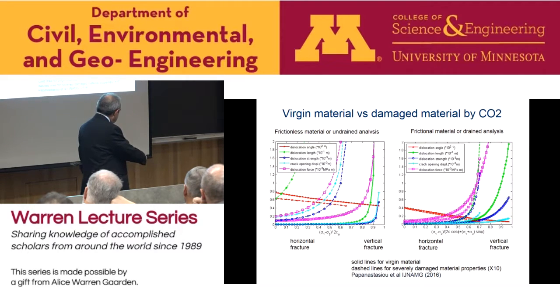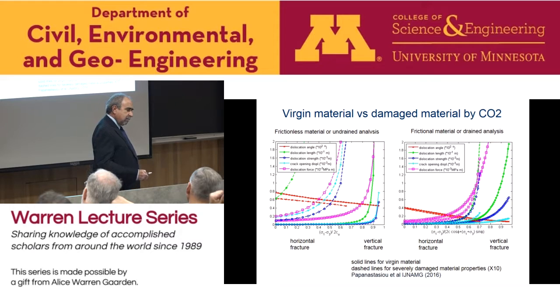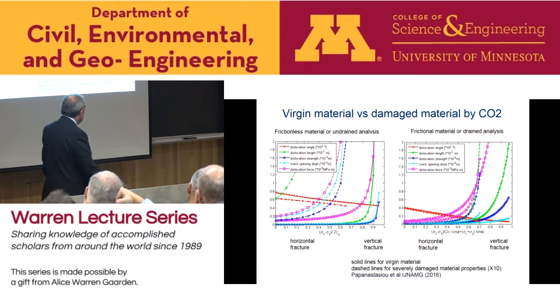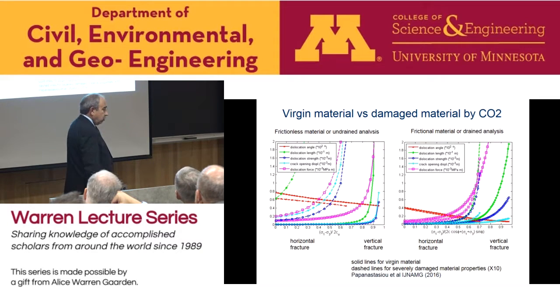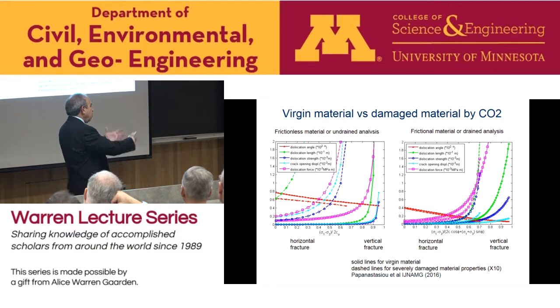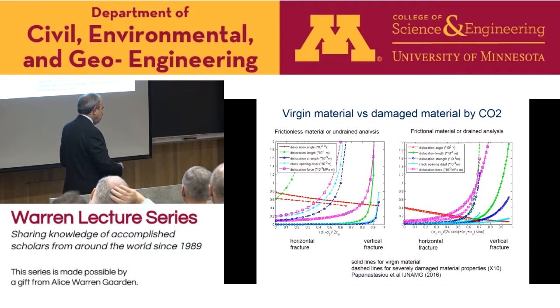Actually, this is a very extreme degree because there are experiments run in different places. They show some decrease in the material parameters, but not to this degree. Anyway, it doesn't matter here. It's calculation. I will repeat the calculations for decreasing both the fracture toughness of the rock and the cohesion to the extreme value. And after we did the comparisons again, we found that for the damaged material, it's even more difficult to propagate a fracture because we decrease the fracture toughness, but at the same time decrease the cohesion as well, so we get more plasticity. We get more apparent fracture toughness, as I showed before, more effective fracture toughness.